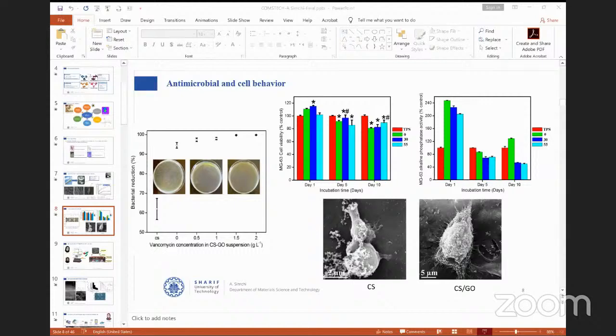We tested the antibacterial effect of such a coating on titanium. As you see in the left-hand figure, the antibacterial effect depends on the concentration of the drug loaded inside the coating. We also did different examinations of the cytotoxicity of the system, because there is always a risk from the nanomaterials inside the coating for biomedical application, and we could not find really an intensive effect on cytotoxicity. On the other hand, we found that the ALP activity is high and the cells stick to the surface, so there should not be a problem.